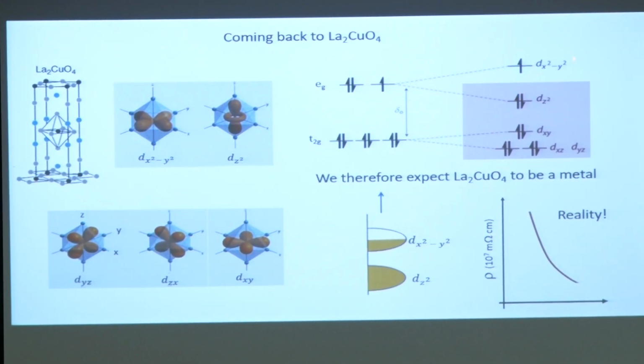So, therefore, you remain with 1 unpaired electron in the x square minus y square orbital, and that is what is depicted over here. So, if you do the band theory, you have a 1/2 filled band, and therefore, this material should have been metallic. But actually in reality, if you measure its electrical resistivity, then it does not behave at all like a metal, but rather behaves like a good insulator, because the electrical resistivity is very high, and also it increases with decrease in temperature.